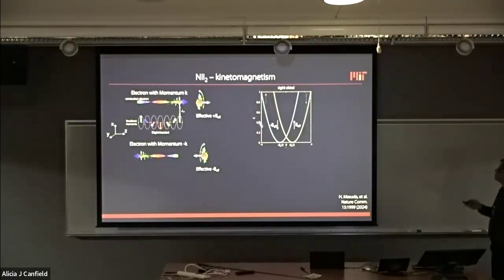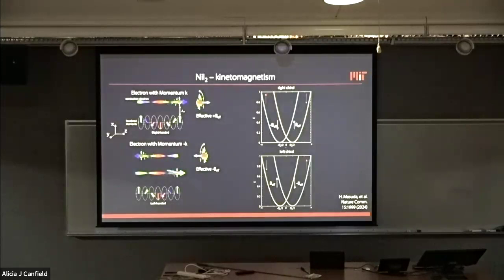So if you look at what this means for the band structure, this means that there is a spin splitting in the momentum axis. So it's similar to a Rashba effect, if you like, but it's due to the spin texture, and it's not really due to spin-orbit coupling. So we can have a spin splitting in the energy axis, which is controlled by energy scales which are much larger than spin-orbit, such as the exchange. And for a helix that has opposite handedness, we have basically the reversal of the spin splitting. So we have up spin and down spin that are split in momentum, but in the opposite direction.